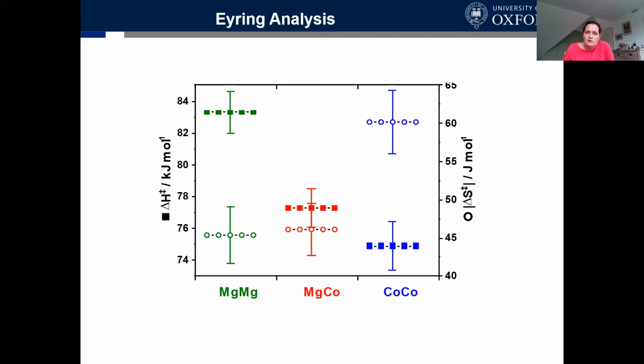And from that, we can deduce the transition state enthalpy and entropy. Shown in solid squares are the enthalpy values, and shown with open circles are the entropy values. What we see here is that the lowest enthalpy is with cobalt-cobalt as a catalyst, and the highest enthalpy is with magnesium-magnesium as a catalyst. Now, of course, you will be aware that the enthalpy has units of kilojoules per mole, whereas entropy is just joules per Kelvin per mole. So the bigger determinant will be the enthalpy, but the entropic factor is important. And we see that the entropic barrier is the exact reverse compared to the enthalpic one.